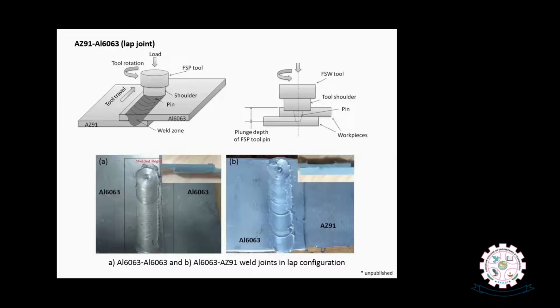Here, a lap joint of magnesium alloy and aluminum alloy was developed by the same friction stir welding process, where we have placed the aluminum alloy sheet on top of the magnesium alloy sheet. Since the aluminum has more deformation compared with the magnesium alloys, we selected the aluminum alloy on top of the magnesium alloy sheet. And you can see the typical photographs and schematic diagrams of the process.